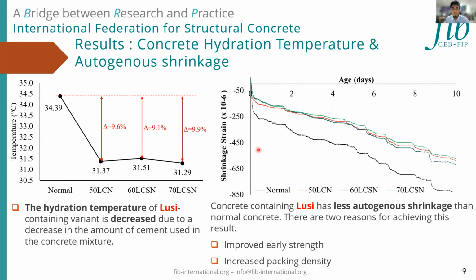And last, this is the result of concrete hydration temperature and autogenous shrinkage test. The hydration temperature test was conducted within the first 24 hours after the concrete was cast, while the autogenous shrinkage test was conducted until 10 days of age. So the thermocouple data show a decrease in the hydration temperature in the Lusi variation due to the lower cement content, which is the primary source of heat.